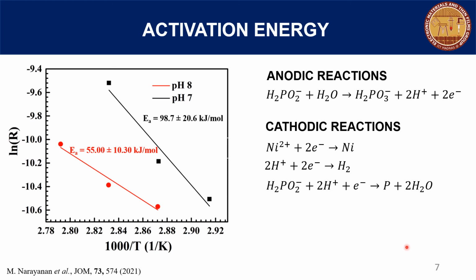In conclusion, we have successfully shown that electroless nickel deposition can be carried out on aluminium without surface activation by using a basic bath. The kinetics of the reaction is surface limited and increases with increase in pH. The nickel reduction and hypophosphite reduction are the rate determining steps in the entire deposition mechanism. In future, we can extend this to aluminum powders as well.